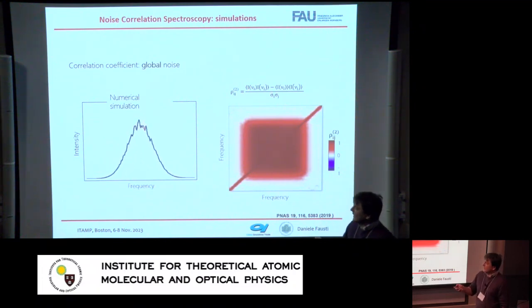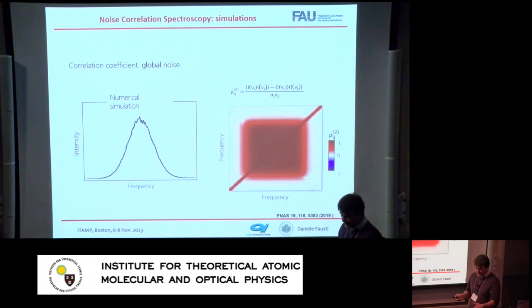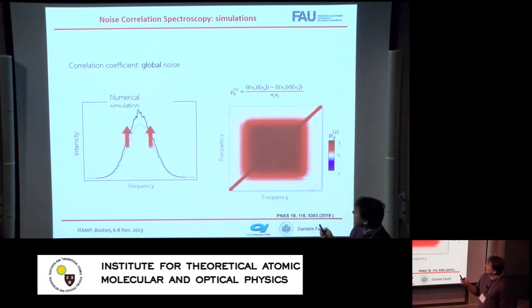I introduce intensity fluctuations in repeated measurements of my light pulse, and I ask myself, how does the fluctuation in one frequency component correlate with fluctuations in another frequency component? And in a frequency plot, I get this blob which actually saturates at 1. And how do I understand it? I understand it because if for a given realization, this spectral component is more intense than the average, this other spectral component is more intense than the average, and that's true for all spectral components.